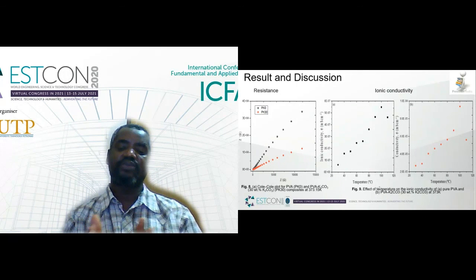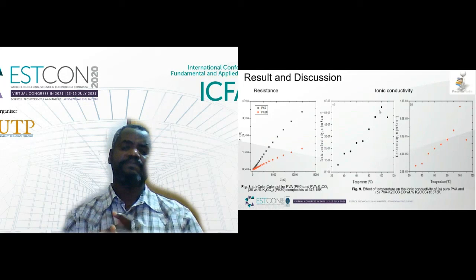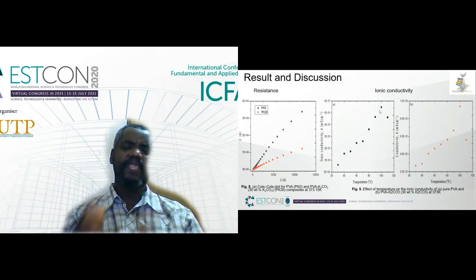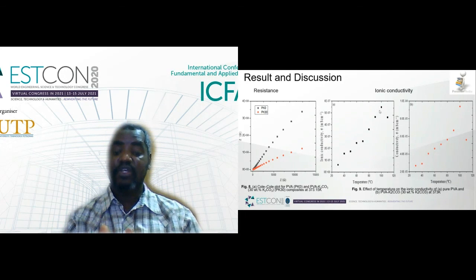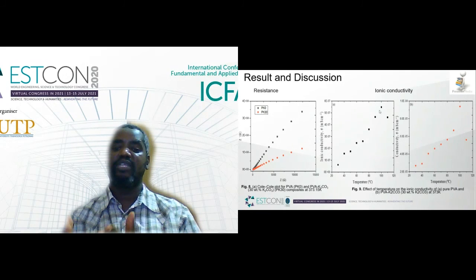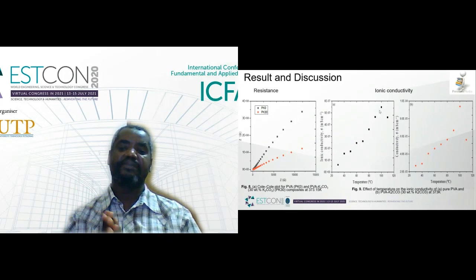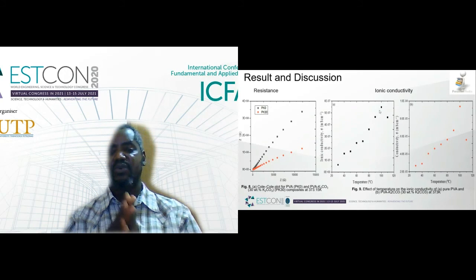As can be seen, ionic conductivity was found to increase with the increase in temperature until we reach 100 degrees C, where the highest conductivity was achieved for both electrolytes. The increase in conductivity with increase in temperature may be connected with the increase in ion migration between the electrode and electrolyte interface. With the increase of thermal activation, there are high chances of ion movement, jumping and hopping between the electrolyte, which may increase the conductivity. However, with further increase in temperature beyond 100 degrees C, we observe a decrease.